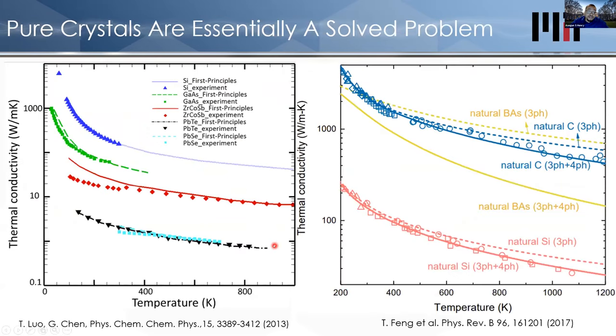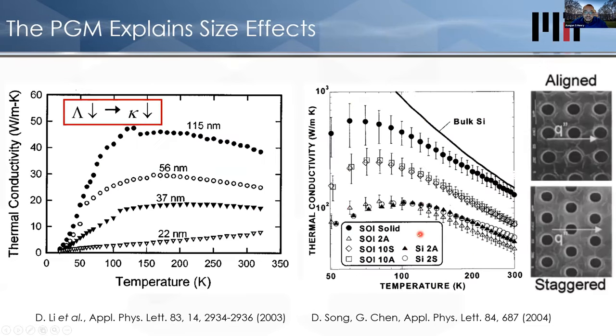Now, the reason people believe in it is, in short, it works. If you look at a crystalline material, these are predictions from first principles calculations, and these are the experiments, and you get excellent agreement between theory and experiments very consistently. So we have great reasons to believe in this. It also does a great job of explaining a key phenomenon you see in nanoscale heat transfer. If you start making something small, then the mean free path, the average distance that these phonons can travel before they hit a boundary, starts to shrink, and therefore the thermal conductivity starts to shrink.